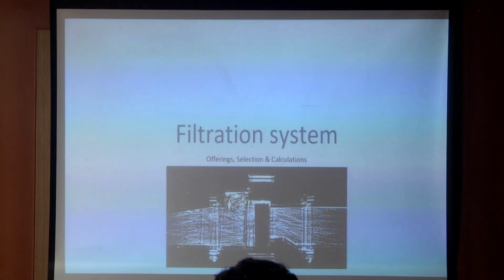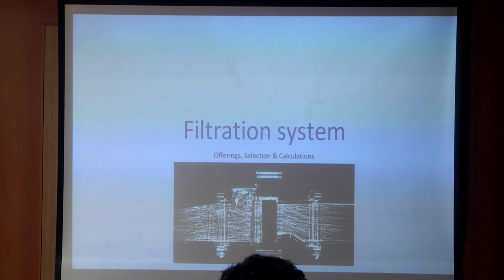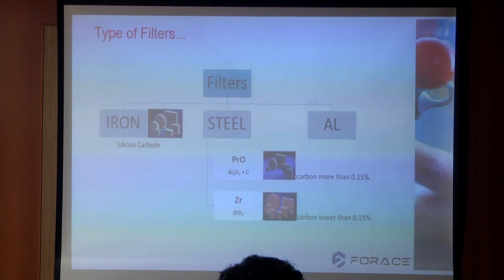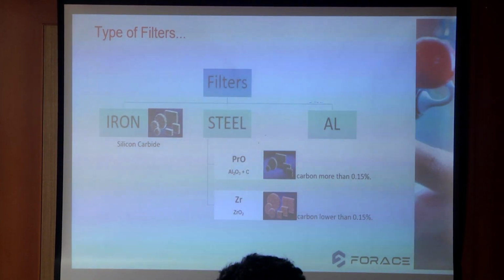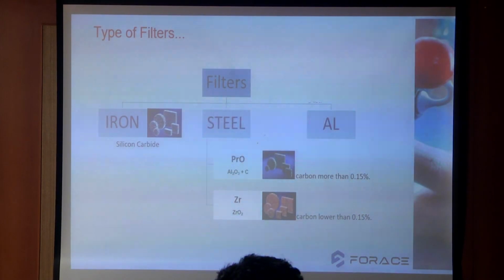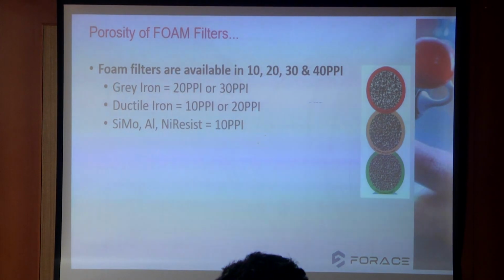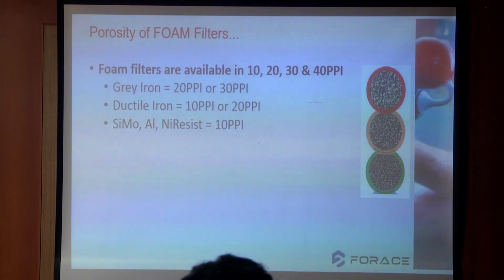So now some technical part on how to select the filters or how to design the running system. In foam filters, we have special filters for iron, special filters for steel, and special filters for non-ferrous. In iron filters, there are basically 10 ppi, 20 ppi, 30 ppi, and 40 ppi. ppi means pores per inch. For grey iron, it is always recommended to use 20 ppi or 30 ppi. For ductile iron, you can use around 10 ppi, or in some cases you can go for 20 ppi also. And in NiResist or SiMo grade, you can use 10 ppi filters.